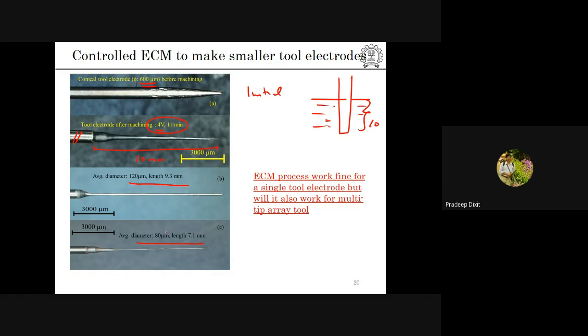For example, here the diameter is 80 micrometer up to a length of 7 millimeter. Here the diameter is going to be 120 micrometer. So it means that by using a controlled electrochemical machining method, it is fundamentally possible to achieve a micro tool electrode. However, at this particular stage, it is still a single tip electrode. We have not talked about any kind of area array.